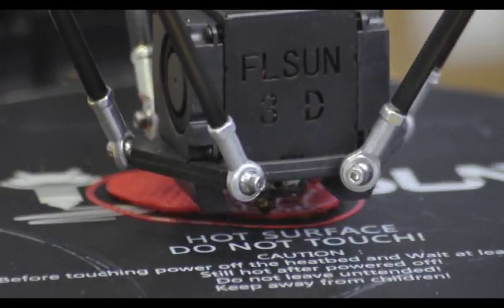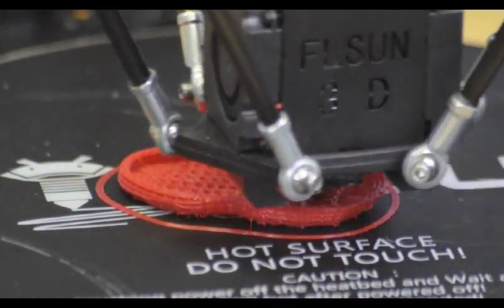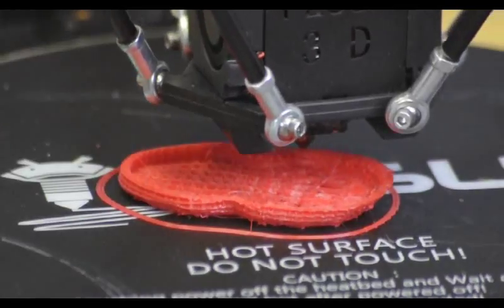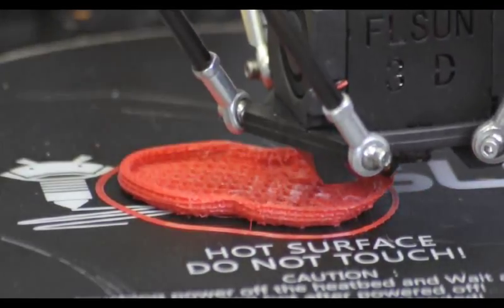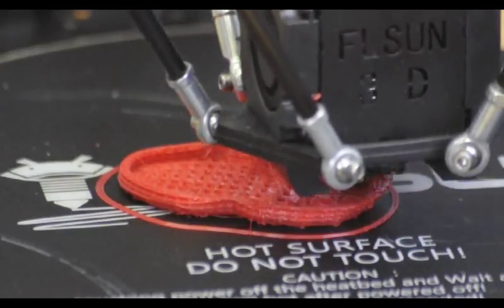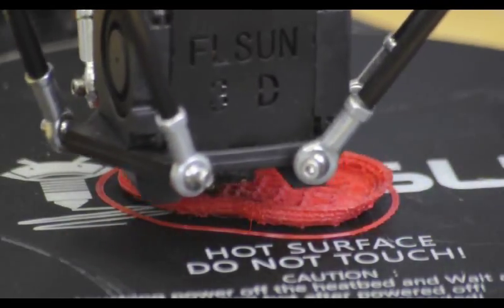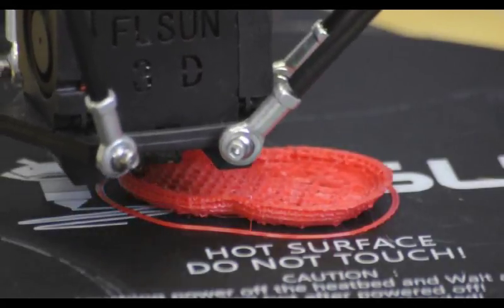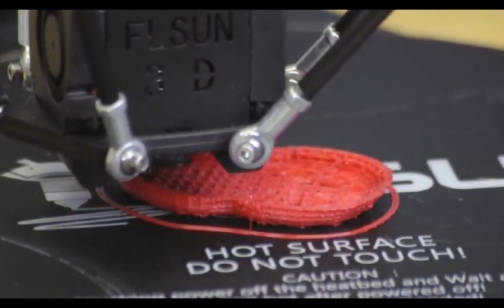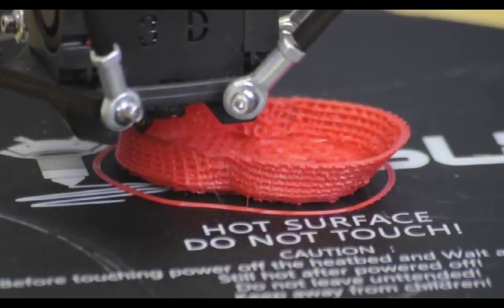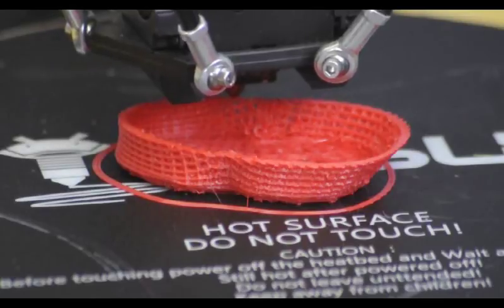Starting the printing process on the QQ involves engaging the autoloading routine to insert the filament. Surprisingly, the extruder had no difficulty feeding the soft plastic through either itself or the Bowden tube. As the filament entered the preheated hotend, I was watching carefully. The last material printed on this machine was MakerGeek's PETG, which has a printing temperature of 255 degrees centigrade, which is the temperature I preheated the hotend to for the loading process so as to be able to purge any remaining PETG from the nozzle. The QQ was able to not only feed the flexible filament into the hotend, it was able to provide enough pressure to purge all of the remaining PETG and start the flow of flexible filament through the nozzle.